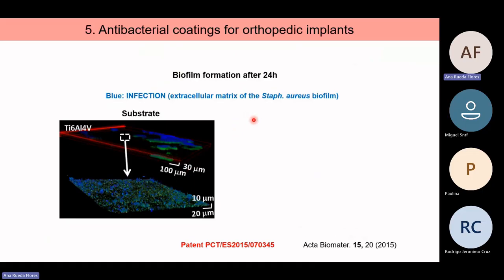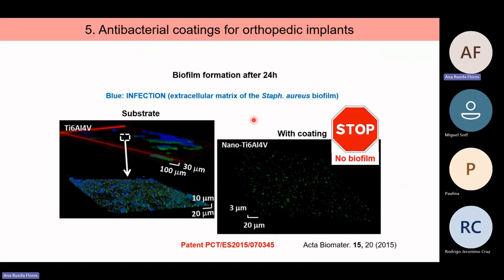When we do the same experiment with the same zoom level on the implant with the coating, you see there is no blue. We still have some alive bacteria, and when we do a careful counting with the software, it's typically between 1/2 and 1/3 of the number of bacteria that are attached to the naked implant. So we are decreasing the adhesion of bacteria. Besides that, the bacteria are uncomfortable and they cannot interact efficiently to form the bacterial biofilm.